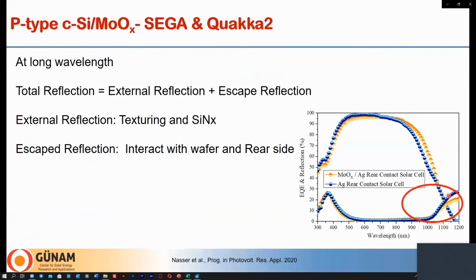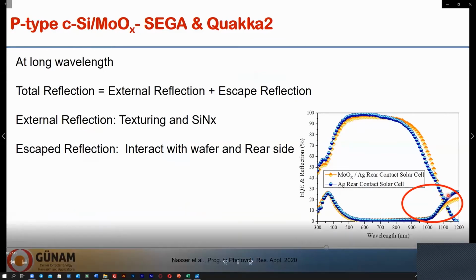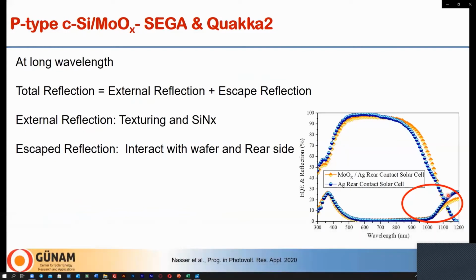So external reflection is correlated to front side texturing and anti-reflection coating, and escape reflection is the light which leaves the front side after being absorbed by silicon, interacting with the backside, and internal reflection from the backside, where at the backside it can be absorbed, can be lost.